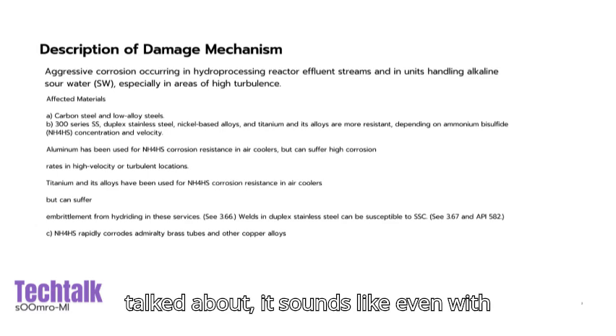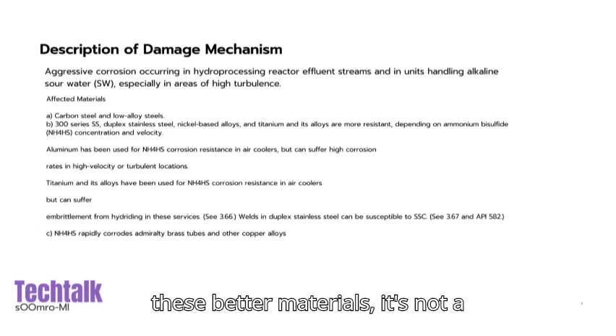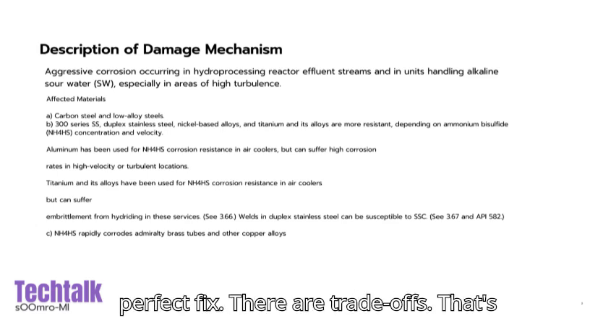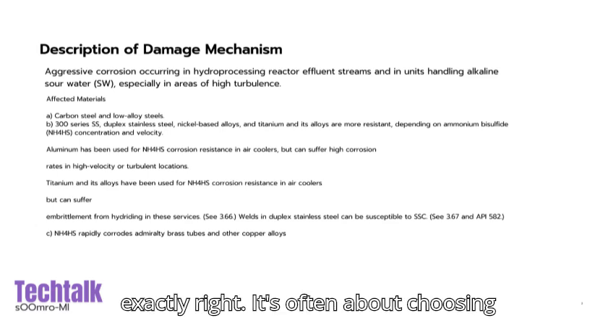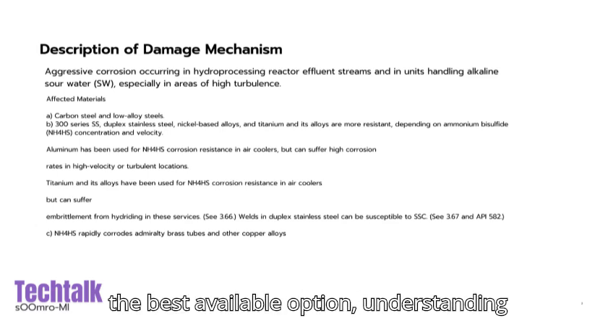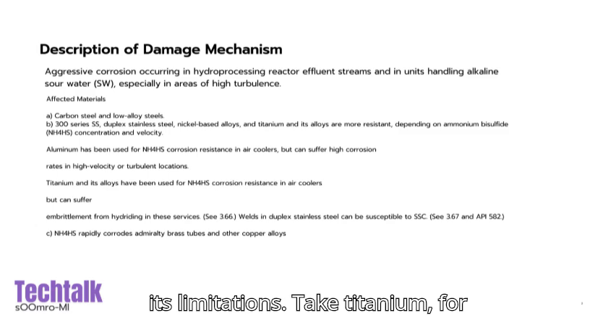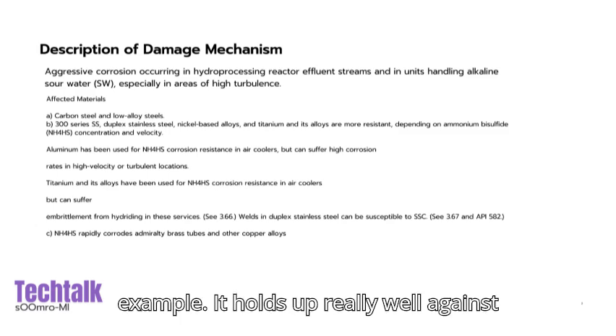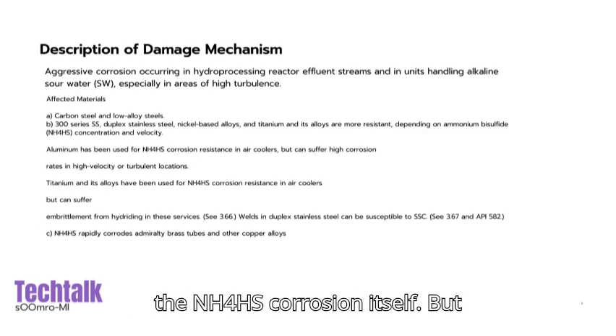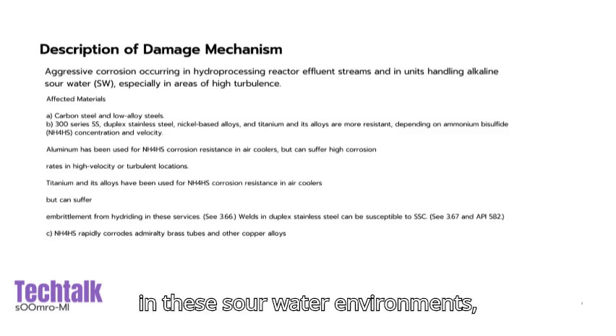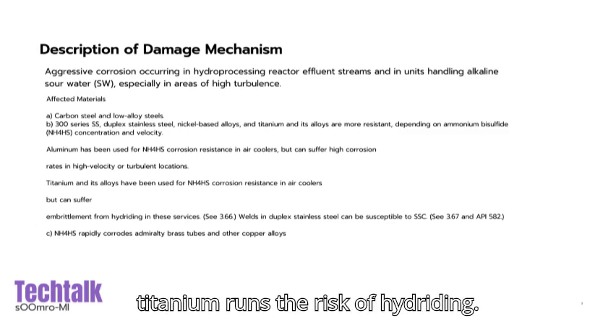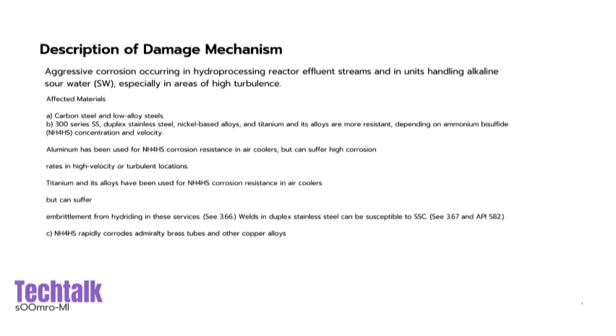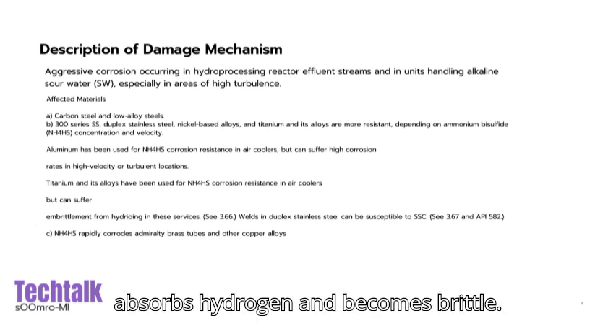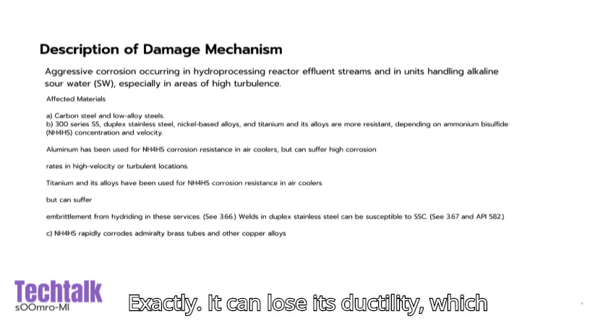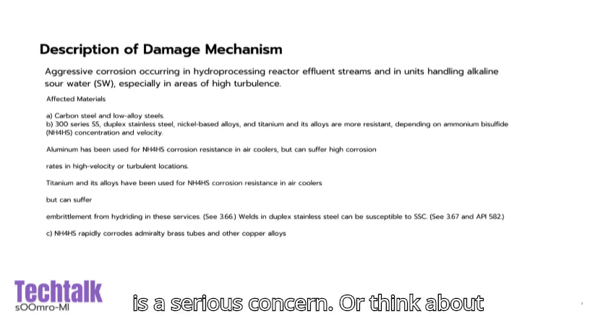It sounds like even with these better materials, it's not a perfect fix. There are trade-offs. That's exactly right. It's often about choosing the best available option, understanding its limitations. Take titanium, for example. It holds up really well against the NH4HS corrosion itself. But in these sour water environments, titanium runs the risk of hydriding, hydrogen embrittlement. Meaning it absorbs hydrogen and becomes brittle. Exactly. It can lose its ductility, which is a serious concern.